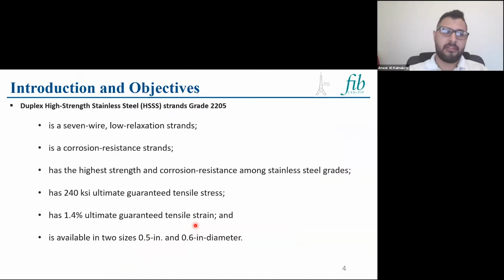One of them is the duplex high strength stainless steel strands, grade 2205. It is a 7-wire low relaxation strand. It is a corrosion-resistant strand, and has the highest strength and corrosion resistance among other stainless steel grades. They call it HSSS. There are other grades, but this is the best option among them.